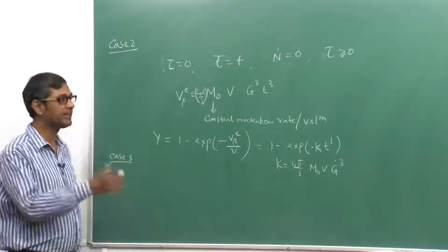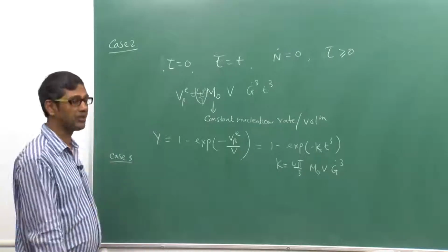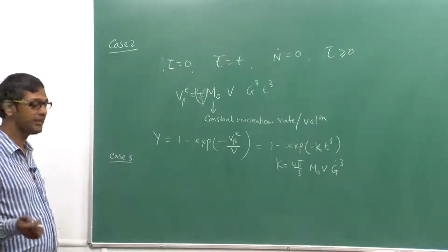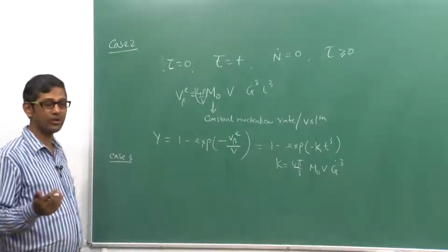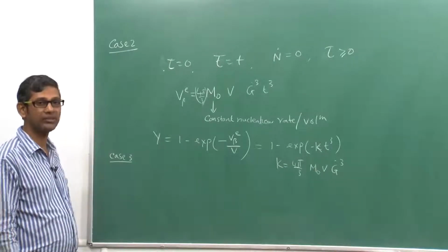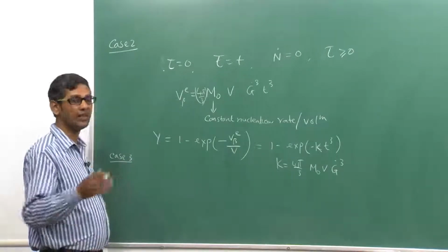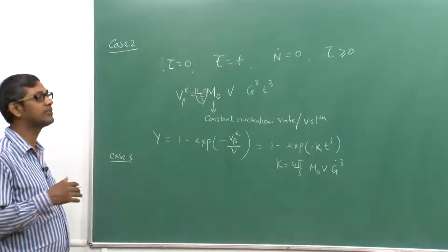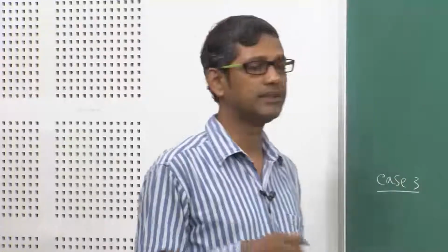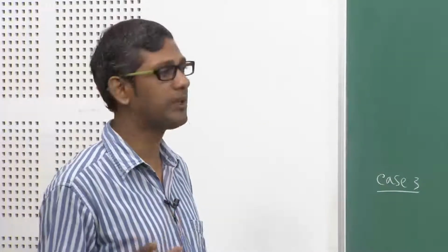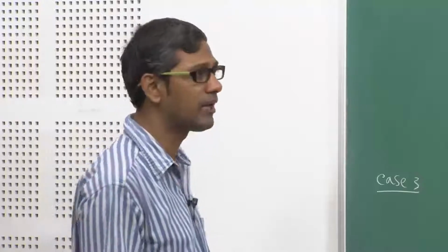suppose you have very small fine grained crystals, okay. That means you have a large number of grain boundaries, because of the fine grains the boundary area is large, and nucleation always happens at the grain boundaries. We know that, or grain edges, or grain corners, or the triple points. These are the places where heterogeneous nucleation happens. So, nucleation will take place randomly if the grain boundary characteristic is random, that means grain boundaries are not special type, not sigma 3 type grain boundaries, they are basically random grain boundaries.